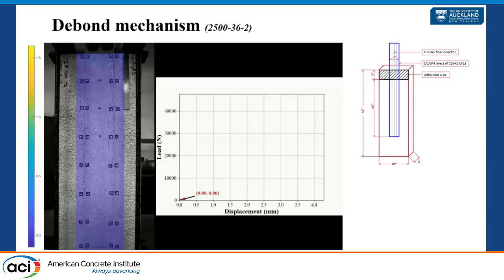It combined with the DIC strain map with the response of load and displacement. In this case, there are concrete blocks with FRP attached to them, and those black dots are targets I mentioned on the last slide. They mark the line between concrete and FRP. If you want to see the sketch of that placement, you can also see the drawing on the upper right corner.